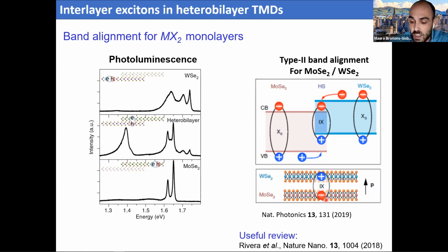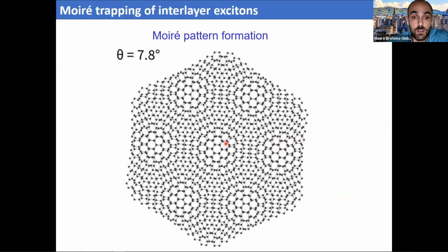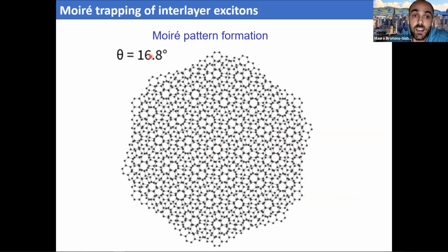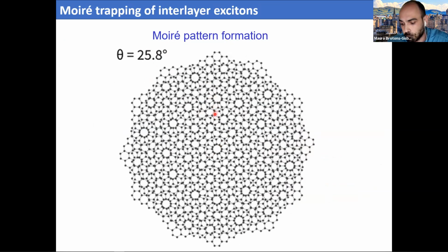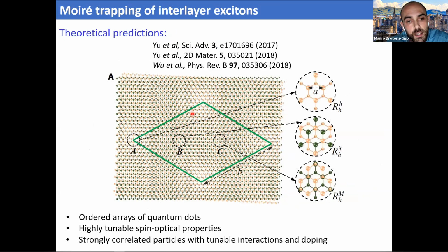On top of that, when you combine two different materials, as we have seen many times in this conference, one gets a moiré superlattice, with a periodicity that depends on the stacking angle and the lattice mismatch of these two layers. It was theoretically predicted that this moiré superlattice should give rise to a modulation of the optical bandgap, and this modulation could give rise to potential traps that could lead to the formation of ordered arrays of quantum dots. In particular, the trapping sites are sites where the atomic registry shows the threefold symmetry of the monolayers that are forming the heterostructure.